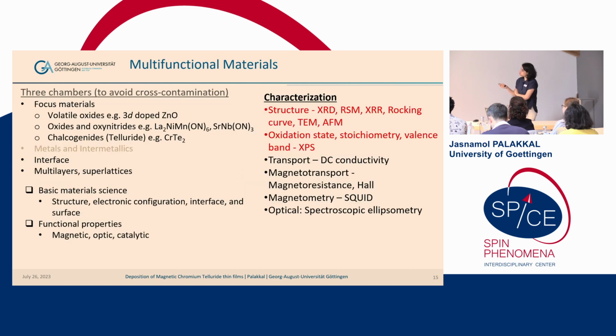So we have 3 PLD chambers, and we are growing different materials in different chambers to avoid cross-contamination. And here I highlighted these 2 characterizations, because when you go for advanced characterization on a material that you received from another group, you always have to verify if they did all this structural characterization at least, because sometimes,